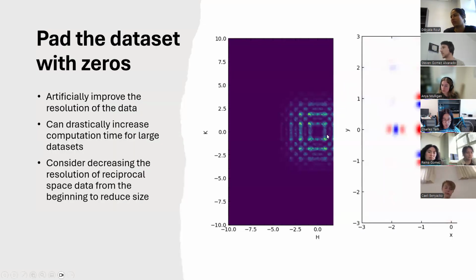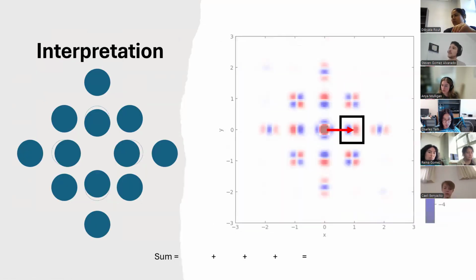It's not as intuitive as you might think. What I have over here on the left is a real space model for a vacancy and the atoms around it that are displacing. The atoms one coordination shell out shouldn't be affected at all, right? These atoms over here are all totally unmoved. Okay, so let's first examine what this little dipole at integer positions means. This is the nearest neighbor correlation.